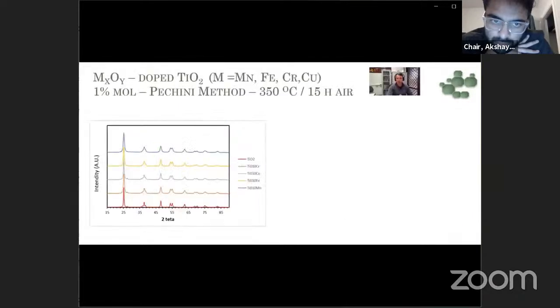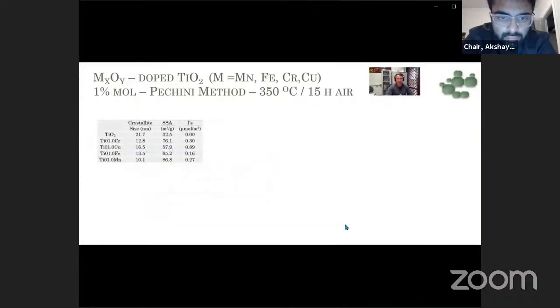We have some results, and this time it is titanium oxide containing some oxides like manganese, iron, chromium, and copper oxide. Then these metal oxides in titanium oxide, all 1% mole, were prepared by the Pechini method at 350 degrees, 15 hours in air. And then we see the same phase, just anatase, okay? And the crystallite size decreases with doping for all samples. The specific surface area increases with doping.